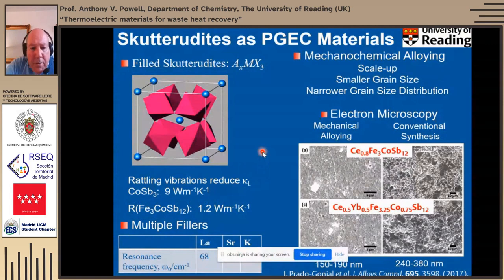So what our interest was really was thinking about, well, if a single rare earth cation with the localized vibrational modes can cause significant reductions in thermal conductivity, what happens if we were to use multiple fillers? Because as we can see here, different fillers have different vibrational or resonance frequencies, and therefore they're going to interfere with different parts of the phonon spectrum.